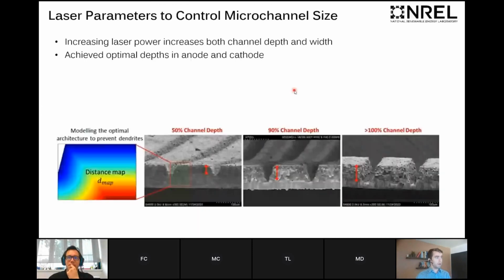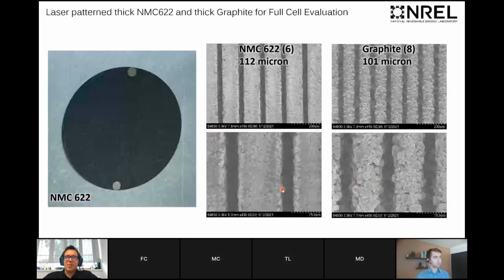And as you'd expect, increase the power, you'll increase the depth and trench width of the laser ablated process. And then the question was, can we control the depth to the extent that we can achieve the 50 micrometers depth on the cathode and 70 micrometers depth on the anode? And we found suitable power and operating conditions that we could achieve that. And so here's an example of how we aimed for about a 50% channel depth, 90%, 100%. We were able to control that fairly well on the shape and size and depth of the features. And these are images of the electrodes that we settled on for actual electrochemical characterization.